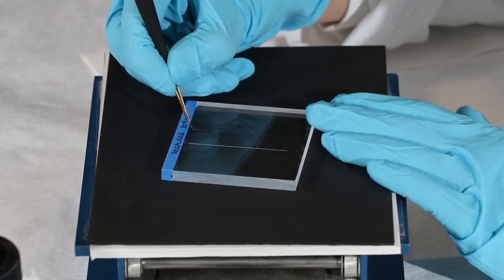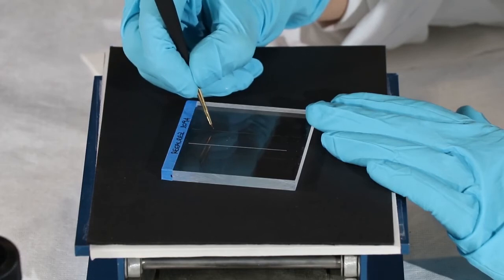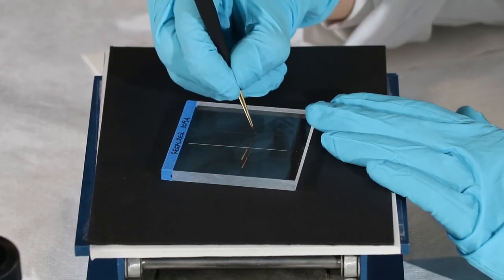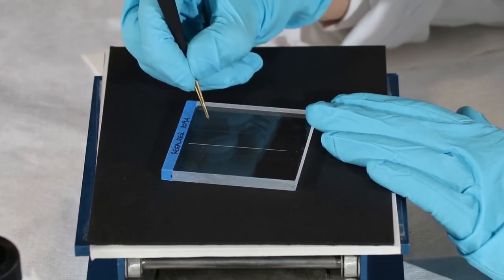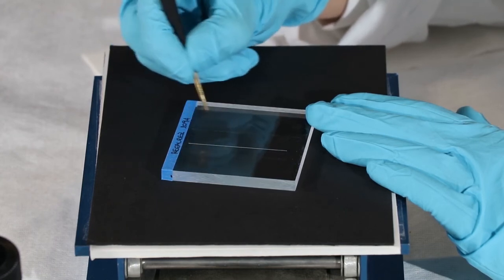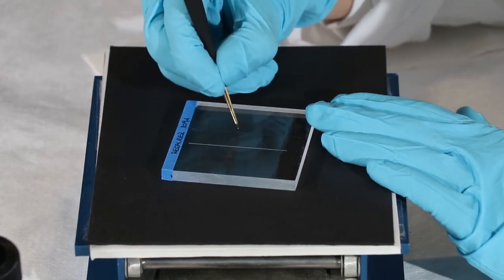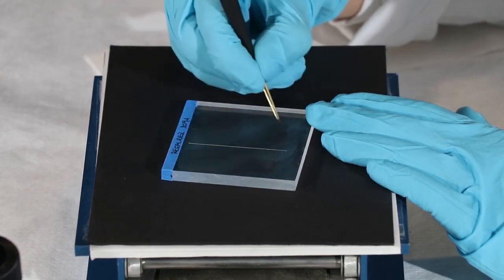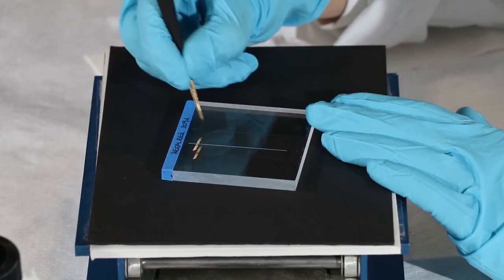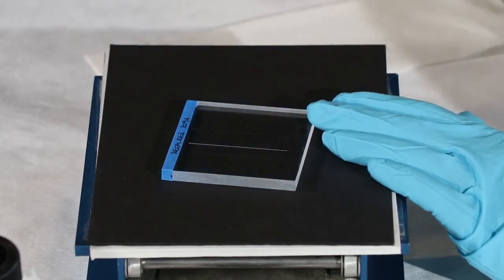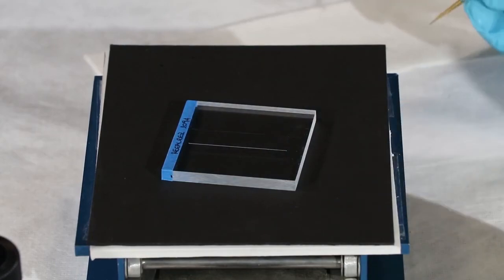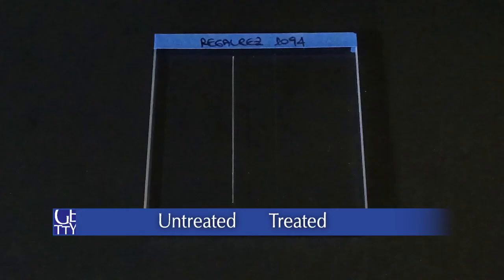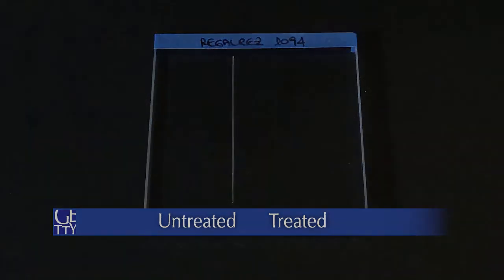Also in this case, one application is generally enough. As you can see, like Hxtal, Regalrez is also able to recover the transparency of PMMA, but unlike Hxtal, it has the advantage of being reversible with solvent, allowing for future retreatment. And here is the result. Note that the appearance will improve and saturation will increase when the solvent fully evaporates.